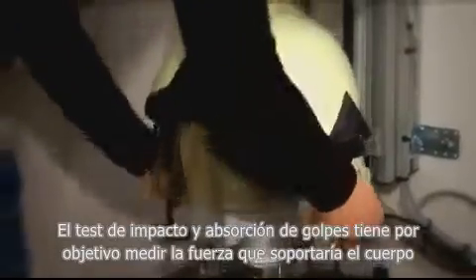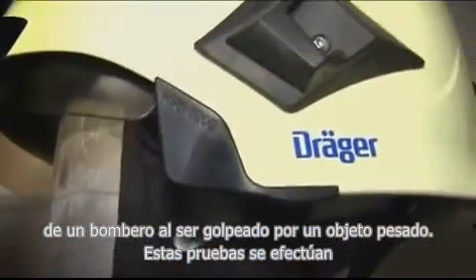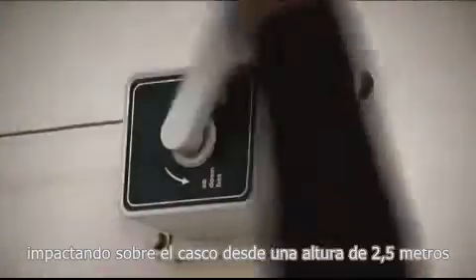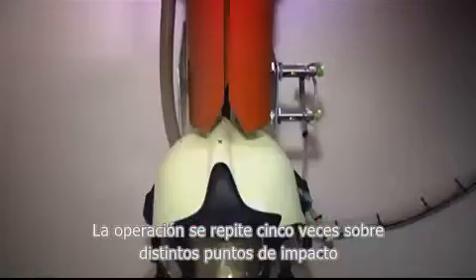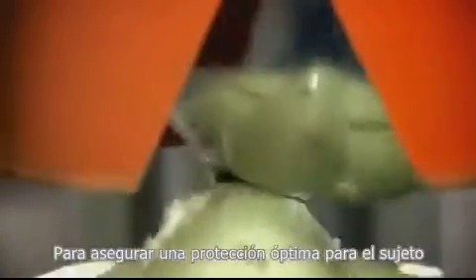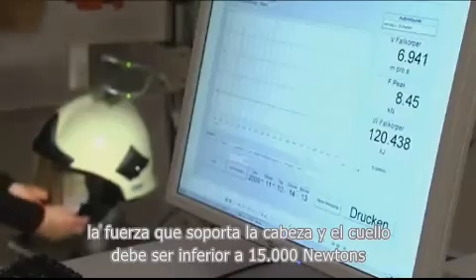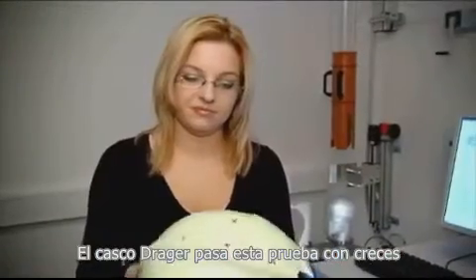The impact and shock absorption test ascertains what amount of force is applied to the body of a firefighter when hit by a heavy object. This test is simulated with a 5 kilogram iron ball impacting the helmet from a height of 2.5 meters, done five times at different test points. In order to provide optimum protection for the wearer, the remaining force on head and neck must be less than 15,000 newtons. The Dräger helmet passes this test with flying colors, yielding values significantly below the required standard value.